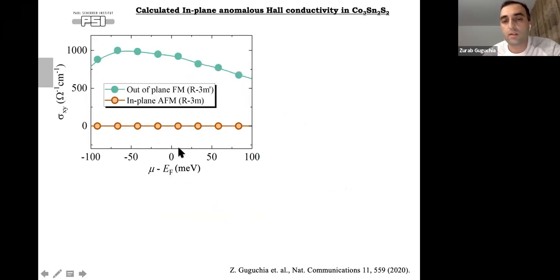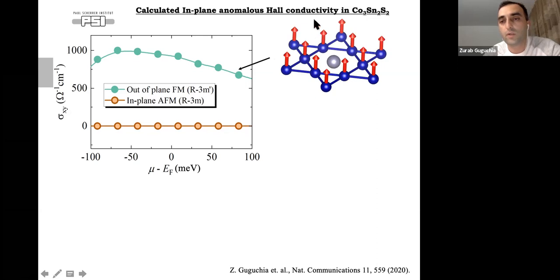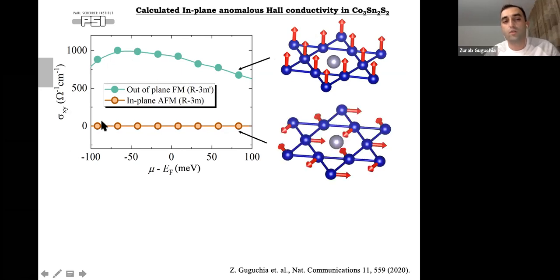Now, how can we understand the suppression of the Hall effect? Using DFT, if you calculate the intrinsic topological Hall conductivity, you see that for this structure it has really the maximum value. It's about 1000, which is what you get experimentally. However, in this structure, the topological Hall effect is completely zero. You may have Weyl points or nodes within the structure, but they are distributed such that the integral of the Berry curvature is zero, so it gives a zero anomalous Hall effect.